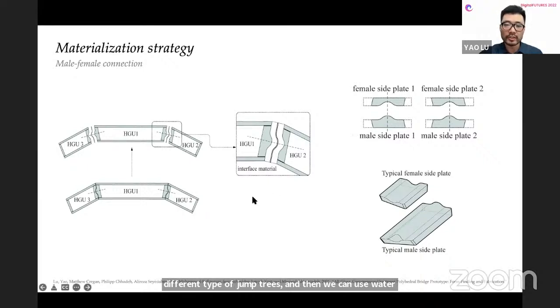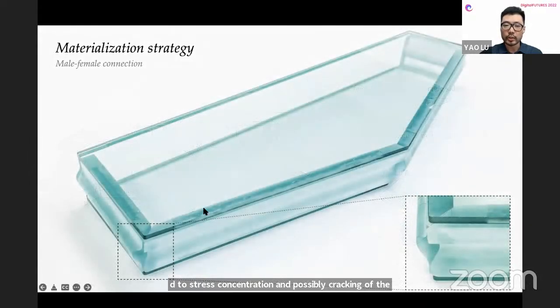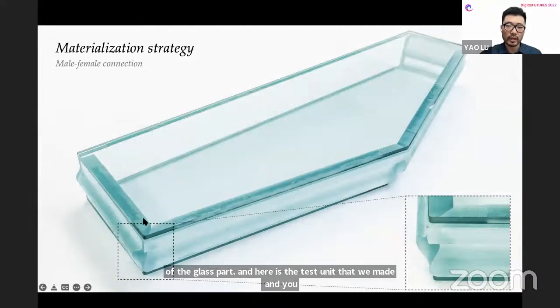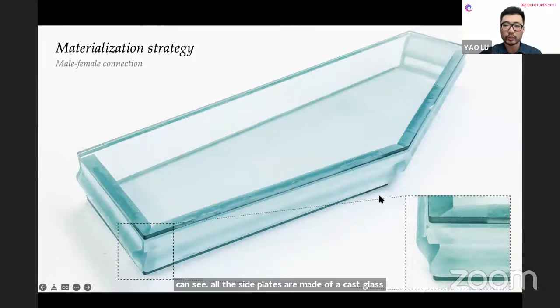One other key element in this connection detail that I want to point out is this little piece of plastic. It's the interface material between the neighboring hollow glass units. It's to separate the glass-to-glass direct contact, because direct contact between glass will lead to stress concentration and possibly cracking of the glass part. And here is the test unit that we made, and you can see all the side plates are made of cast glass and 5-axis water jet cut.